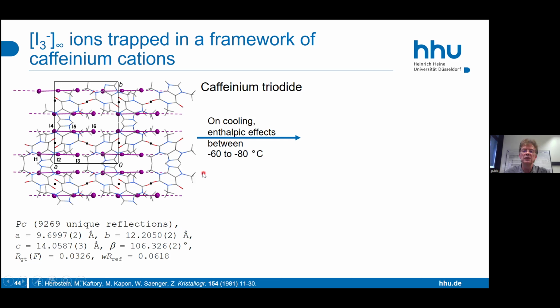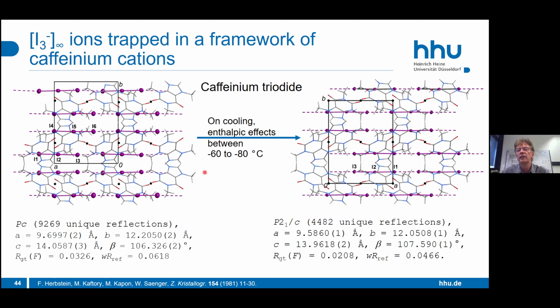What we did then was we cooled it down and were surprised that we got a single crystal to single crystal transformation. And at the end, we have, again, the same framework. So you see here the inversion centers of the framework. But now the I3- ions are perfectly within the symmetry. Perhaps we go to this inversion center and you see this I3- here and here downstairs. Yes, here and here. So perfect.